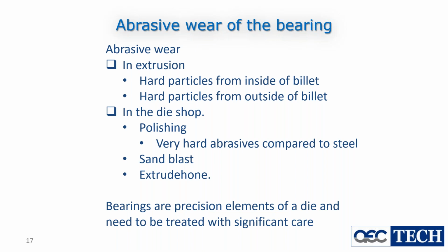I have to put forward that it should not be anything harsher than ANSI 600, which is ISO 1000 paper for polishing. We've had several webinars on this, and I made presentations in ET paper. There's a lot of very good data that shows if you are wanting to polish the bearing, you shouldn't use anything more aggressive than ANSI 600.